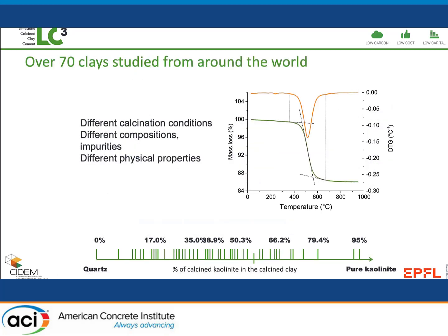So we've now tested more than 70 clays from all around the world. People said to us, clays are so variable. This is true. They have many different minerals present. You can quite simply measure the kaolinite content by looking at the weight loss between about 400 and 600.